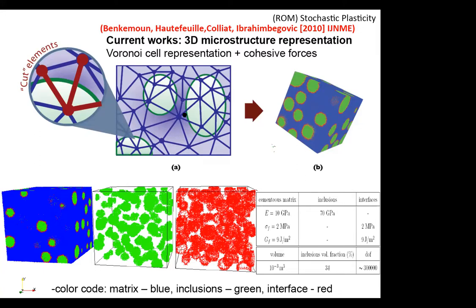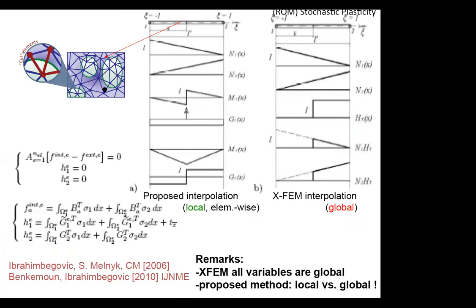So you end up having cohesive links, which are supposed to be modeling the fracture, in 3 different locations. There's one which is completely in the aggregate. This one is considered to be elastic. It doesn't break. The one which is completely in cement, this one is elastoplastic, it can break. And the most interesting one is the interface. Part which is in the violet color can break, and part which is in white color cannot break. So basically, you have to represent this most complicated behavior. In other words, the one which is a little bit in aggregate, a little bit in cement. For this one, we introduce this jump that is supposed to be handling the breaking point.